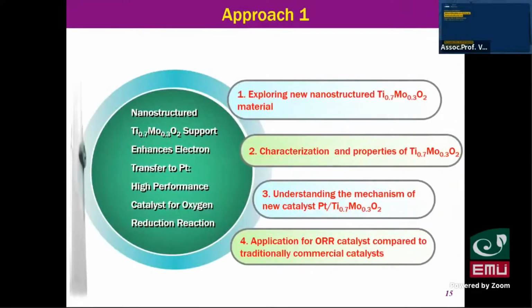Our approach: we explore the new nanostructure, molybdenum doped into titanium oxide, with a ratio of 0.3 molybdenum and 0.7 titanium oxide. We study the characterization and properties of this material. After that, we disperse platinum catalyst on the new nanostructure to replace the carbon support, and we apply it for ORR in PEMFC. We compare our catalyst performance with the commercial catalyst, Pt on carbon.